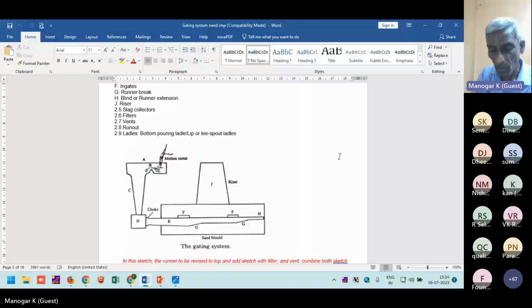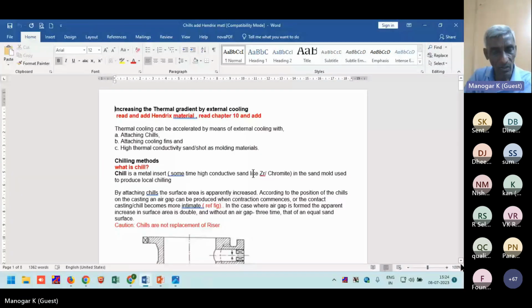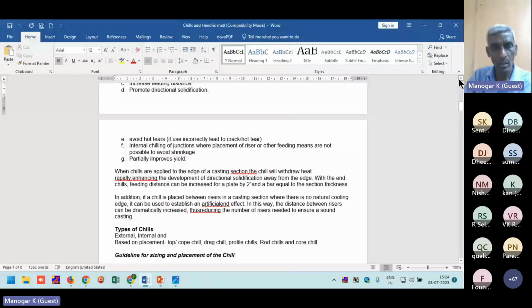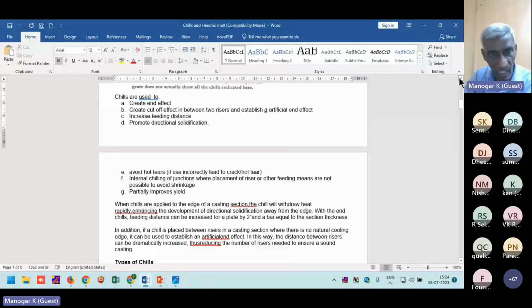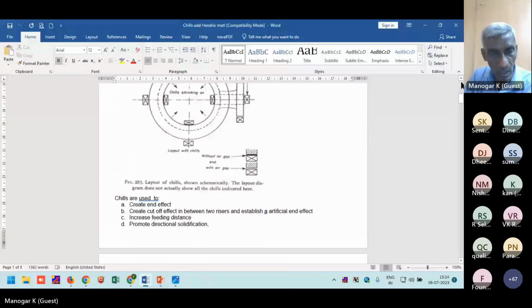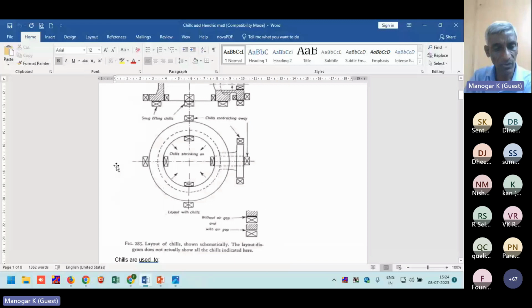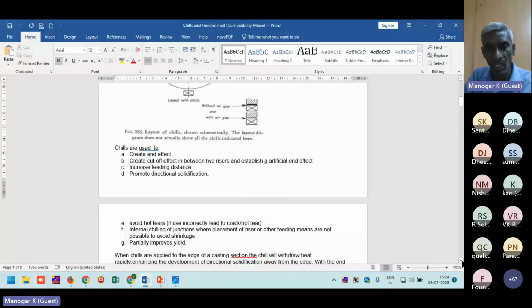For that, we discussed the chilling methods. When we are using chills, there should be an air gap, and that will have a lesser effect. How to keep chills and the effect of chills you can also see. Chills are used to create an end effect, create a cutoff effect in between two risers, and establish an artificial end effect, increase feeding distance, promote directional solidification, avoid hot tears, internal chilling of junctions, and partially improve yield.